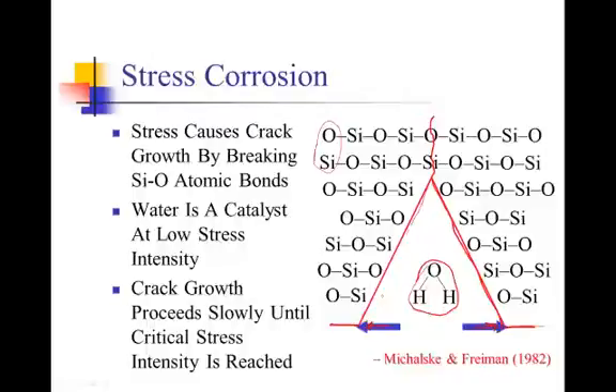What can happen with the water in the environment is that it can penetrate to the crack tip, and because water is a polar molecule, the slight positive charge on the hydrogen ion will be attracted to the negative charge in the oxygen anion in the ceramic and will form a bond with it, and the slight negative charge in the oxygen anion of the water will be attracted to the positive silicon cation and form a bond with it. And this acts as a catalyst and reduces the stress intensity factor that's required to break apart the silicon and the oxygen.